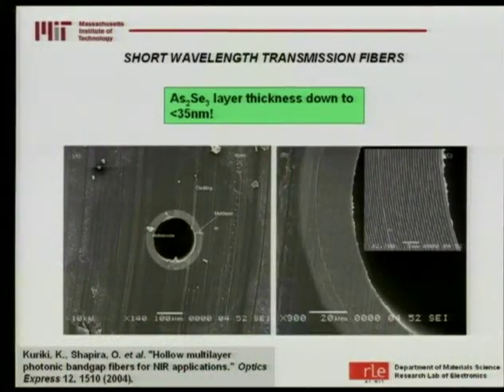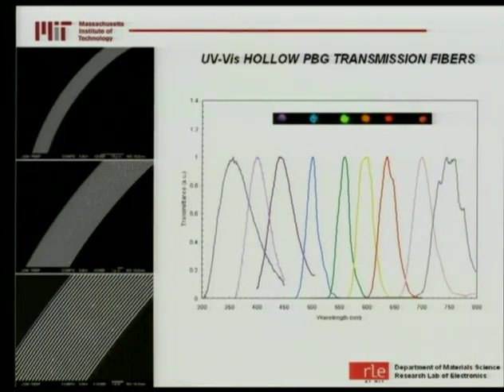Since that work was published 3 years ago in Nature, we went on to construct fibers at significantly shorter wavelengths. Here's an example of fibers that conduct light not only in the infrared, but down to the visible and even in the UV. What you can see is we've gotten much better at putting in many, many layers. This is a section of the fiber, and the layer thicknesses are very, very reproducible.